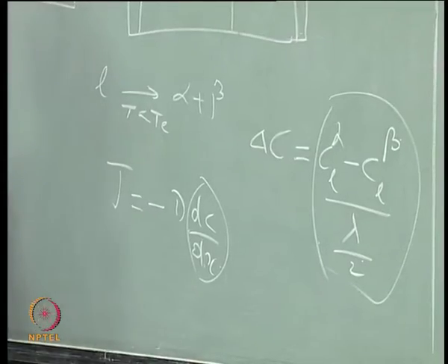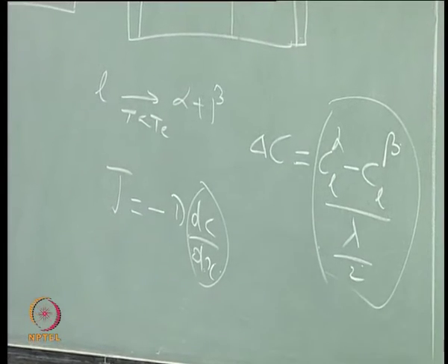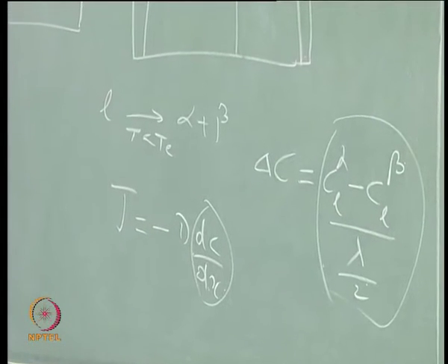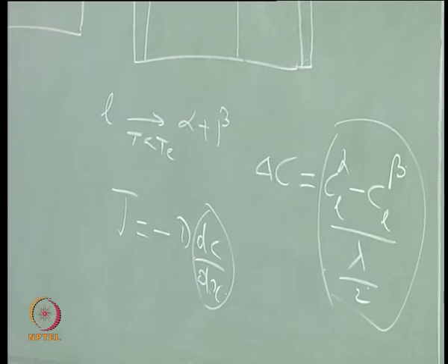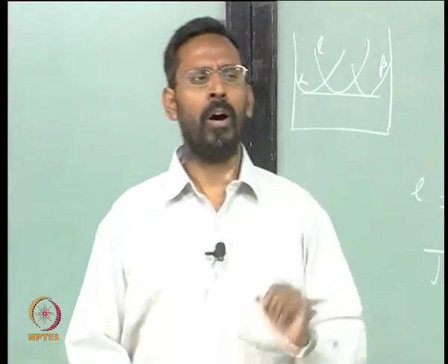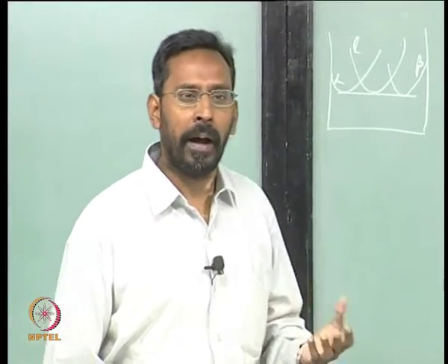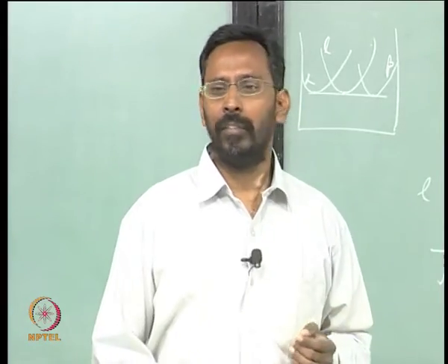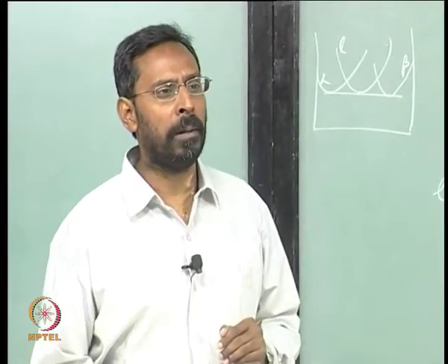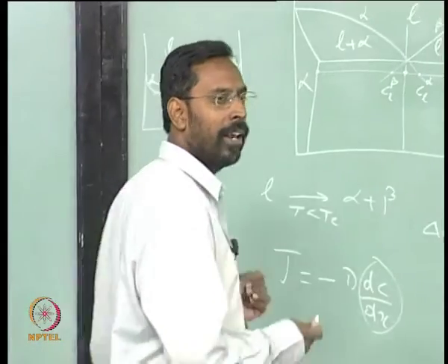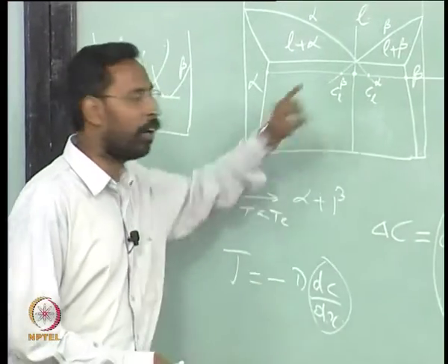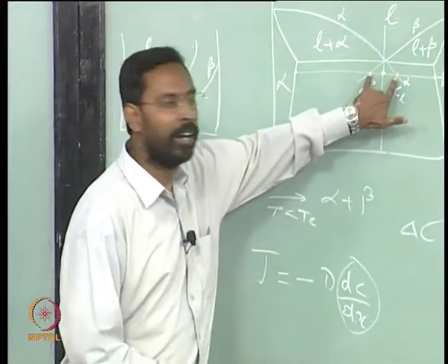So in principle, at the eutectic you cannot have growth, you need a small undercooling, at least a small undercooling. It can be very small if heterogeneous nucleation is available, otherwise it can be slightly large, but you need a small undercooling so that you have a driving force.